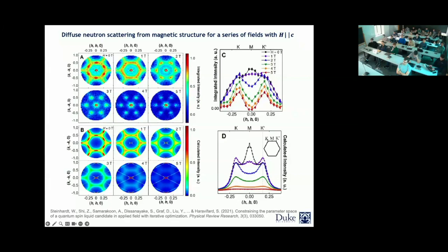They used the model that was already predicted for this compound, which is an XXZ model. And then they said, okay, when you have this XXZ model, let's look at it in 2 ways, quantum fluctuations or site disorder. And through both of them, we were able to replicate the zero field data.